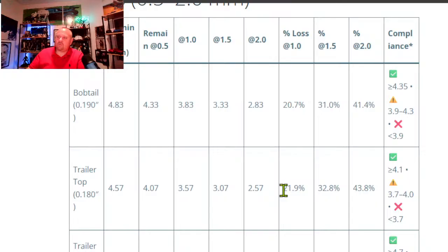At 1 millimeter removal on a tanker trailer, you're at a 21.9% reduction in wall thickness. At 1.5 millimeters, you're down to 32.8%, and 43.8% with 2 millimeters removed. Anything at 4.1 or above is ideal as far as your thickness. Anything between 3.7 and 4.0 is reason for concern and inspection. Anything less than 3.7 millimeters thick is non-compliant. So when you're looking at any of these numbers, they cannot be sanded. They really shouldn't.